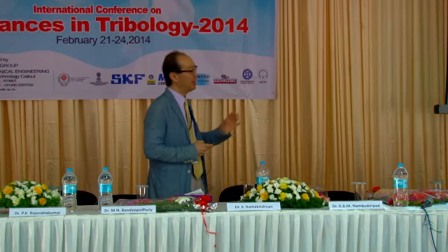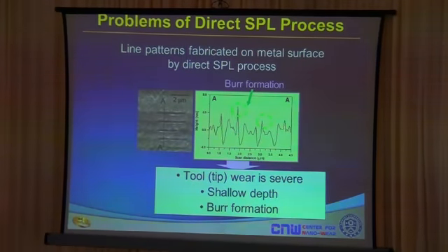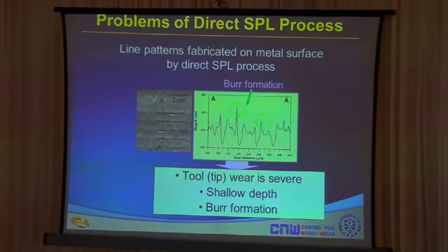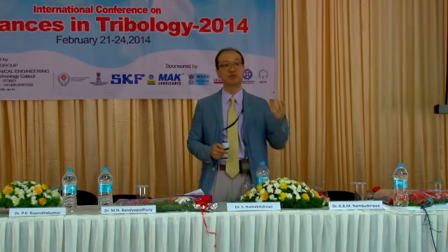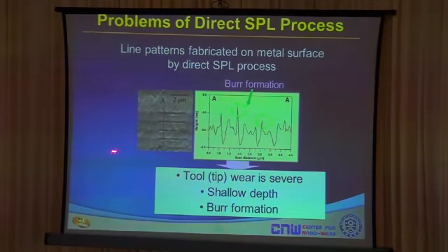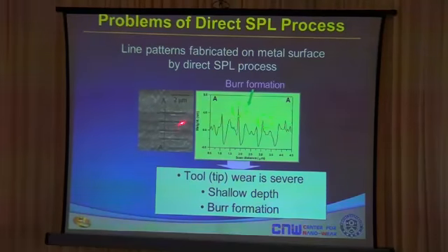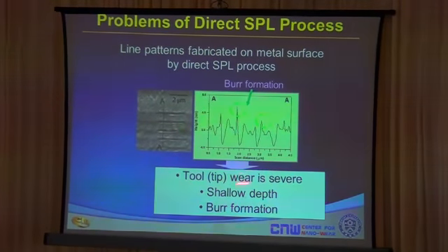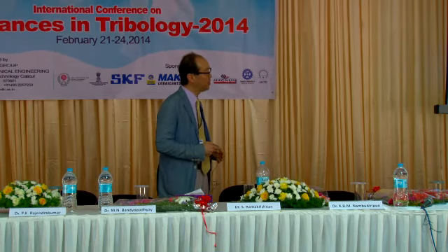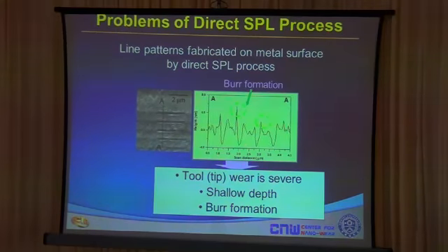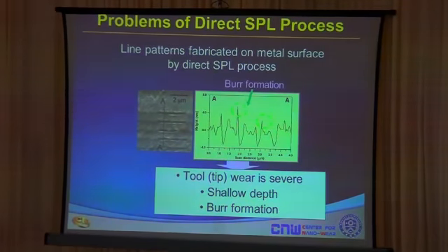So the concept was to apply this kind of wear process for lithography, and many people have done that, and it's sometimes called direct scanning probe lithography. Basically, you take a very sharp AFM tip and you scribe against the surface to create very fine patterns on your surface. Now, the problem with this process is because of the wear I showed you earlier, when you create these small patterns on the surface, you experience a very large amount of tool wear because of high pressure, and also you have creation of burrs at the surface, just like you would create burrs in typical mechanical machining or grinding process. And also, the amount of depth of cut you can achieve is very shallow because of the limited force that you can apply to the tip, otherwise the tip will break.